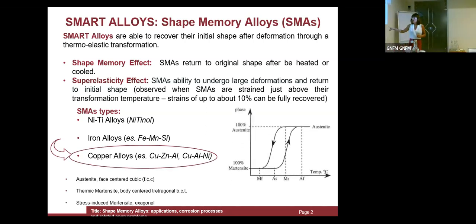Okay. Here I would like to show you the austenite martensite transformation curves. The possibility to recover the initial shape is due to the austenite martensite transformation. The austenite is a stable phase at high temperature, and the martensite is a stable phase at lower temperature. And here we reported the percentage of austenite and martensite according to specific ranges of temperature. With a certain hysteresis, so the possibility to have both austenite and martensite is possible in some specific range of temperature.